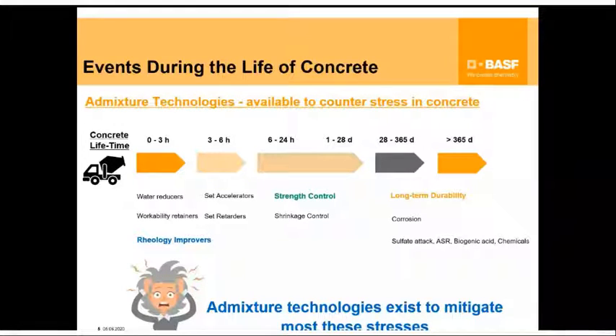So these are properties that today we are able to manipulate with cementitious system and concrete, which allows us to separate the ability of water to give workability out of the workability equation. So today, water is not the main component of getting workability. There are other tools available that can bring these properties while maintaining some of the benefits of low water to binder systems. Then from 3 to 6 hours, we are talking about the hardening phase. You can either accelerate it or retard it. We have systems, tools that allow us to do that.